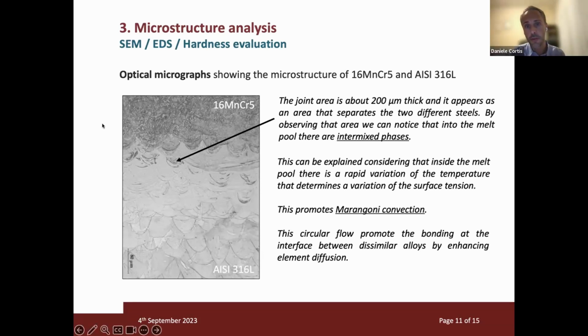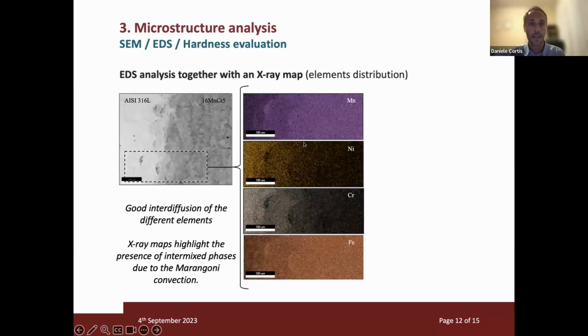So the thickness of the junction probably confirms the depth you have when a laser passes over one layer above another layer, which is usually 3 or 4 layers. We print these components with a layer of 40 microns, so 4 or 5 layers is the depth that the laser track can reach. And here is the EDS analysis, which confirmed the good interdiffusion between the steels and the different elements: manganese, nickel, chromium, and iron, of course. And here you can also see the Marangoni effect described before.